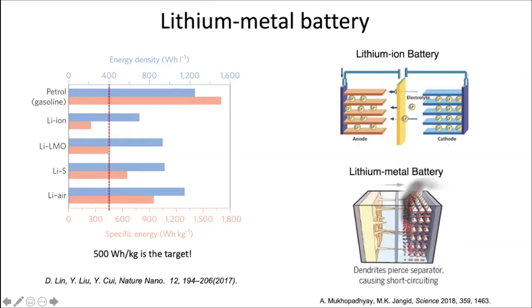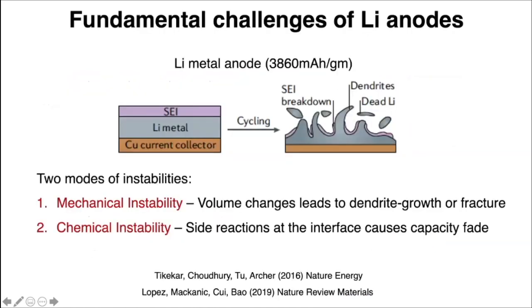And in addition to that, during this growth, all kinds of side reactions might happen, and lithium might grow into dendrites and then cause shorting and a lot of issues with stability and safety. So that has been the main challenge in bringing the lithium metal anode into practical application.